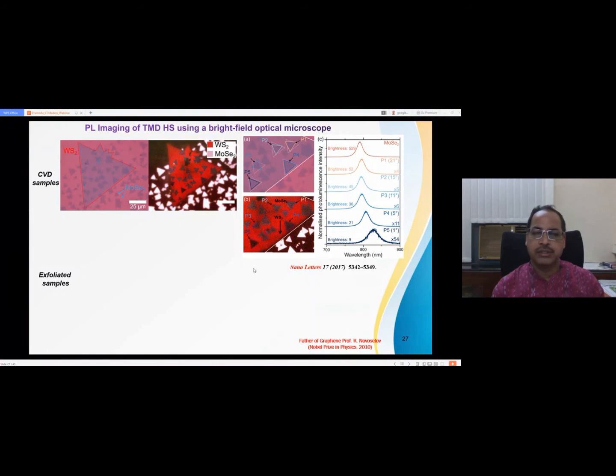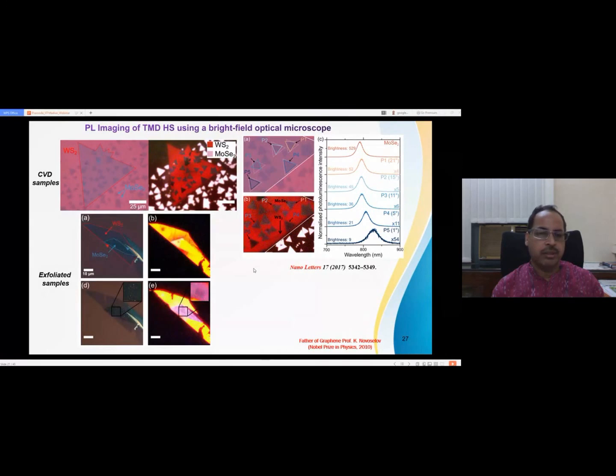And we have also done this with the exfoliated sample. This is MoSe2 and WS2. After annealing, you can see, and we also do the PL imaging. There is a large contrast in the heterostructure. The PL intensity diminishes.